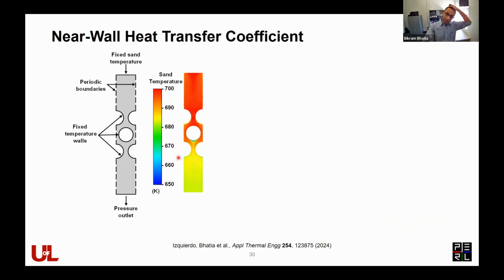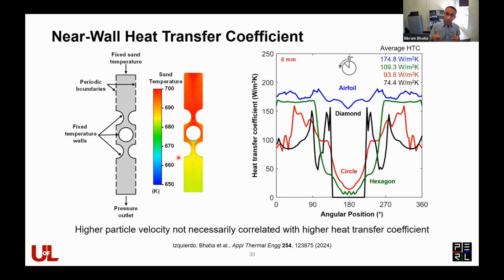So we took that model and added the energy equation and mimicked the CSP operating conditions, and we evaluated what the particle to wall heat transfer coefficient was. We went into this expecting that the configurations that give us higher velocity will give us a higher heat transfer coefficient, and maybe that's true for some of the regions, but on average, we see that the airfoil geometry actually gave us a much higher heat transfer coefficient. It has to do with the kind of flow that it promotes.